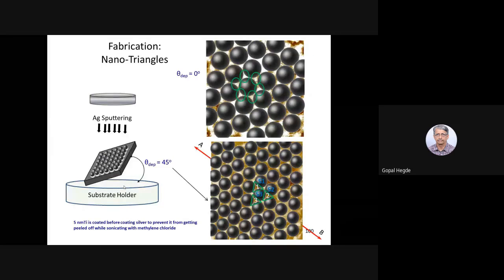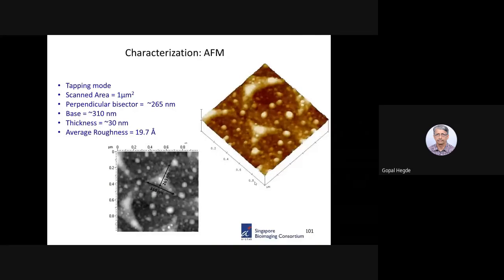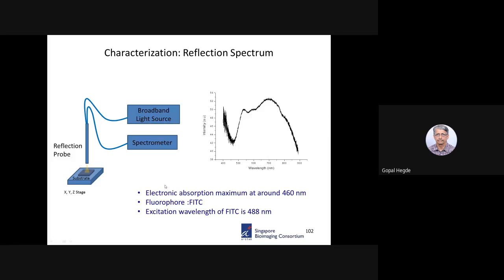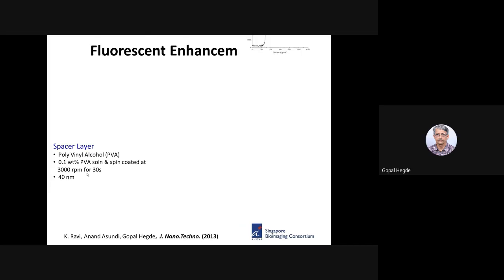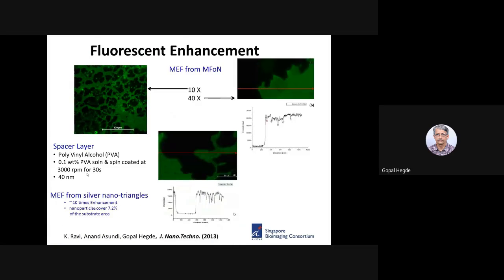I am not going into the details of these fabrication processes. You can use a variety of techniques to make silver nanoparticles these days, and this is where we consider this as a nano triangle. We fabricated these nano triangles, and using the atomic force microscope, we measured all these things: approximately 265 nanometer, 310 nanometer base. Later we put the biomaterials on top of these nano triangles. Then we saw the fluorescence enhancement. This is where the fluorescence enhancement was observed.